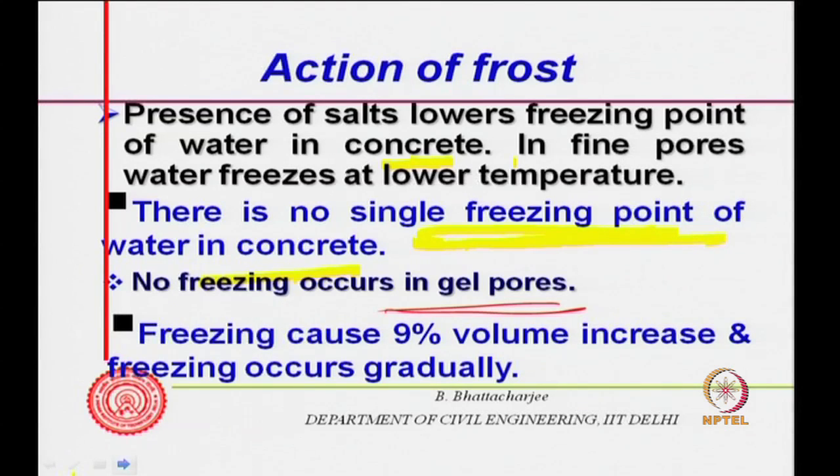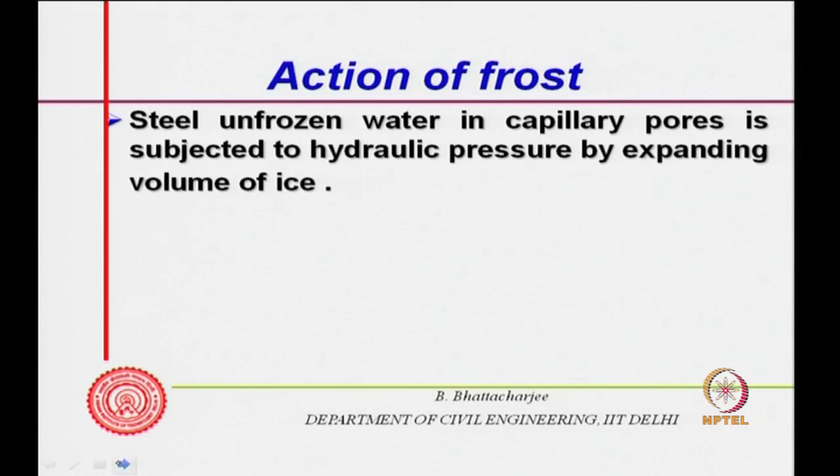Now, when freezing occurs, it causes a 9% volume increase, and freezing occurs gradually, because the water in all the pores will not get frozen in one go. So, there is a 9% volume increase. Now, this volume increase actually causes an excess pressure. The water in unfrozen capillary is subjected to hydraulic pressure by this expanding volume of ice.